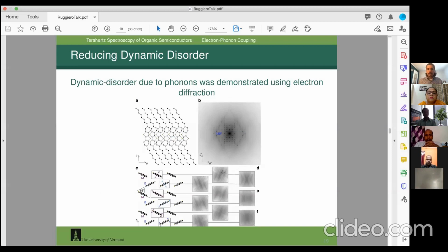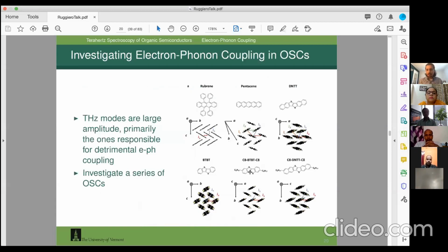And they showed that in this case, with these BT-BT and C8 BT-BT materials, as you alkylated the semiconducting core, they saw a reduction of some motion and an increase in charge carrier mobility. But that's about as much as they could understand. They didn't know what motions there were. They just knew there were motions in one plane of the material.